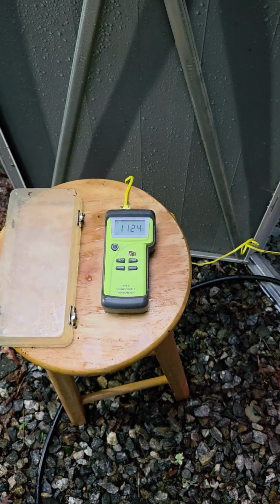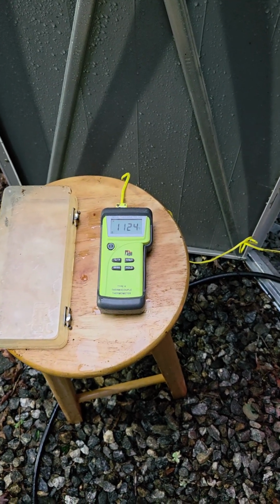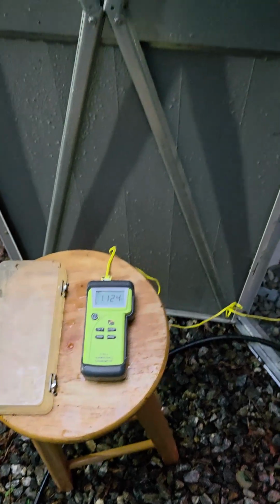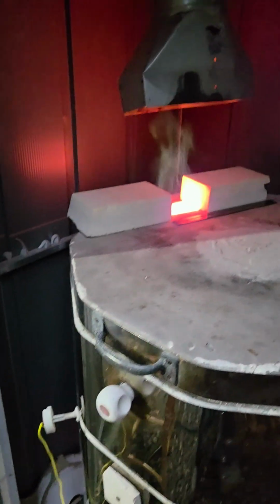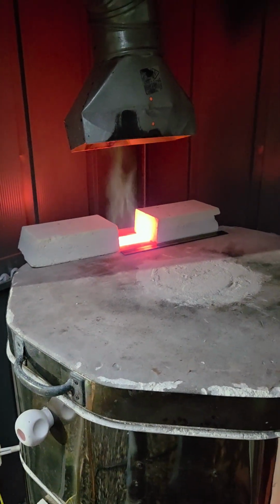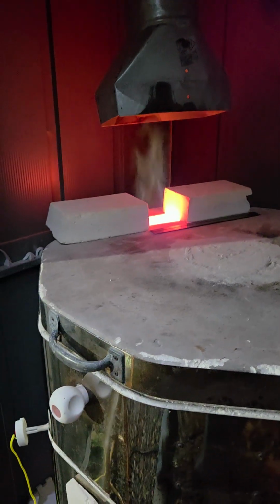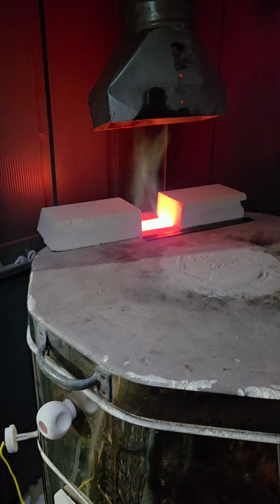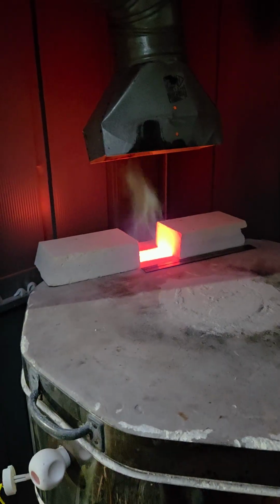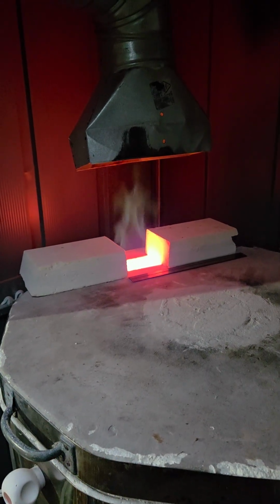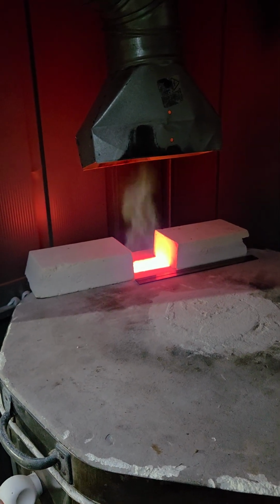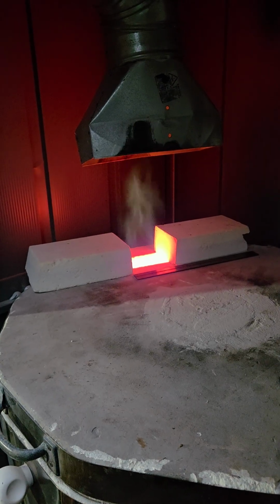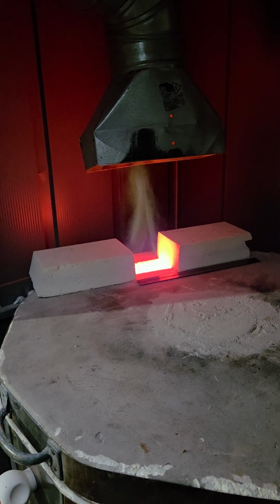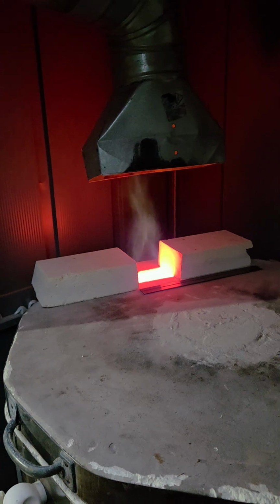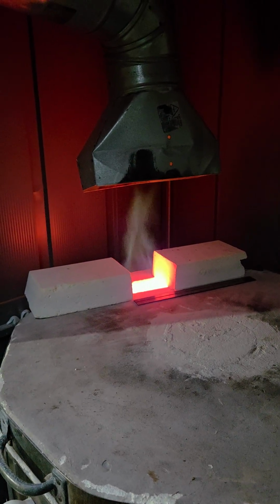So it's at 1,124 degrees centigrade now, and it's about 15 minutes after I made that last adjustment. I've got a good reduction flame, but it slowed down from about 146 degrees per hour climb 15 minutes ago. It's already slowed down to about 130 degrees per hour climb, as I just did another timing check.